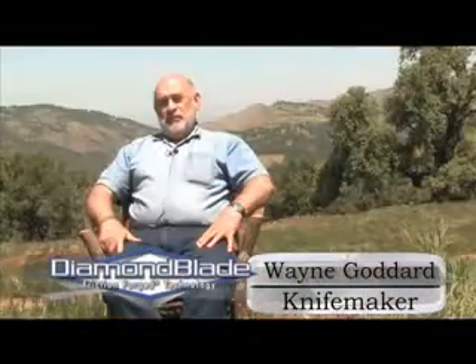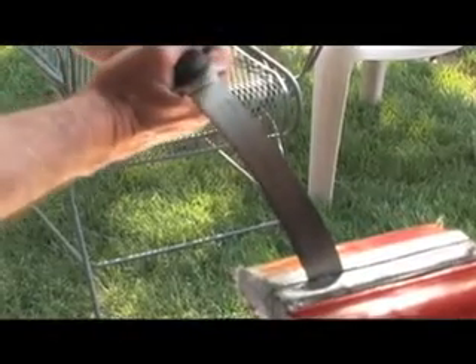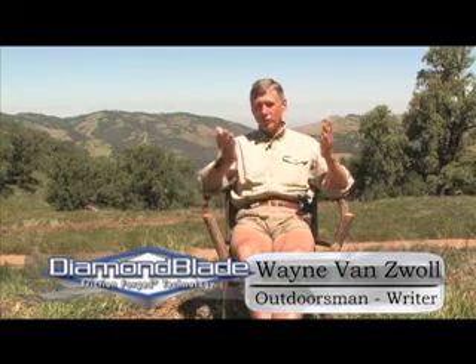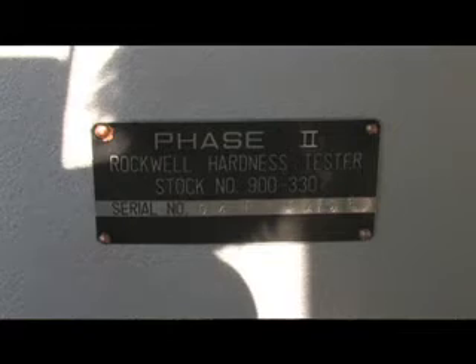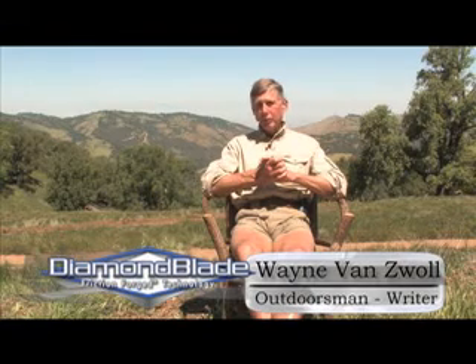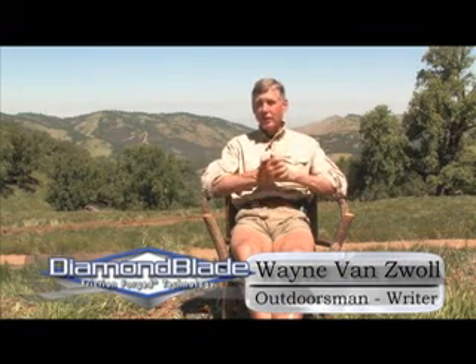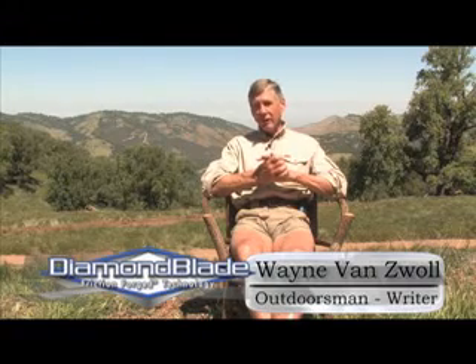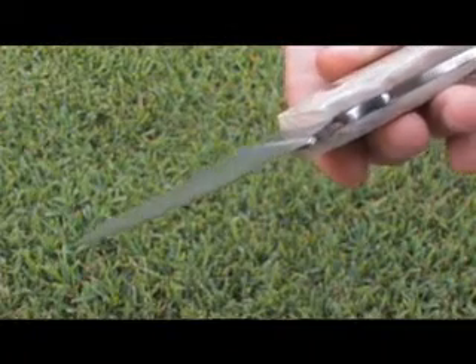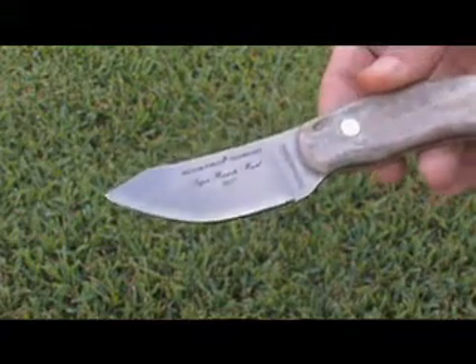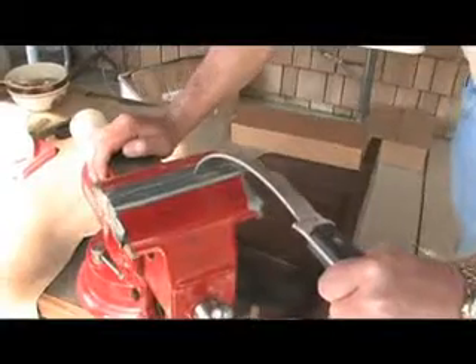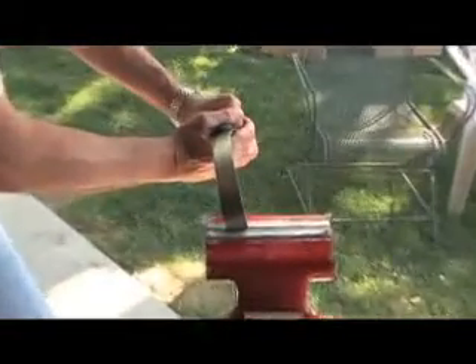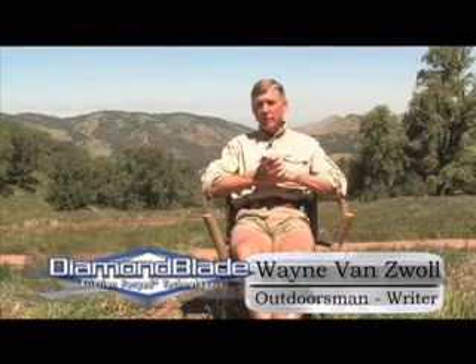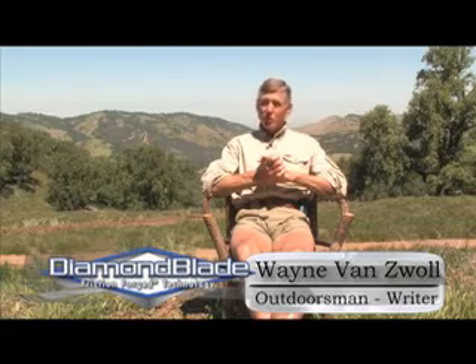Fine grain means it can be harder and have sufficient strength. The flexibility of this blade is astounding, and yet the edge is much harder. You're looking at a Rockwell rating in the mid-40s for the spine of the blade, which gives it a lot of resilience and ruggedness. But a Rockwell C of 65 on the edge, which is where you want hardness. Now the edge is not brittle. It's amazing that this blade can bend without affecting the contour of the edge. So the edges stay sharp, and they're very hard. So that's just what you want in a hunting knife.